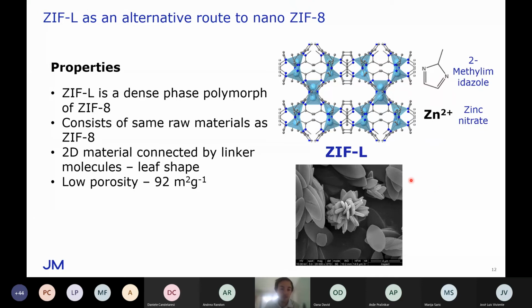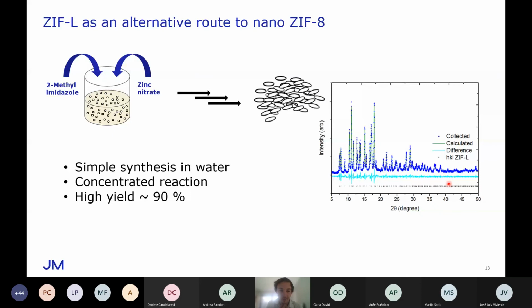ZIF-L also produces very large, leaf-shaped particles, which makes it not applicable to our membrane application. It also has very low porosity, only about 100 meters squared per gram versus the 1,000 or 1,500 in ZIF-8. However, we can make ZIF-L quite easily using a very simple synthesis, again a simple precipitation type synthesis in water. So we mix our 2-methylimidazole and our zinc nitrate. We can do this in a very concentrated reaction and produce nicely phase pure ZIF-L in very high yields, up to 90%, which is brilliant for us, especially as we avoid the use of solvent. We can use water instead.